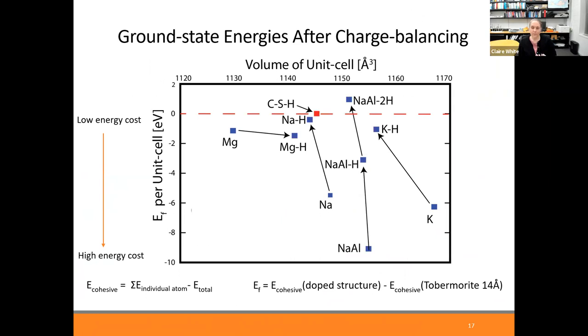So just to recap, what we found is essentially a charge balancing mechanism whereby if you replace a calcium atom with a sodium atom, if we have a hydrogen atom that's in the vicinity as well, that's added, then we end up with a stable structure that's comparable to the initial tobermorite crystal structure.